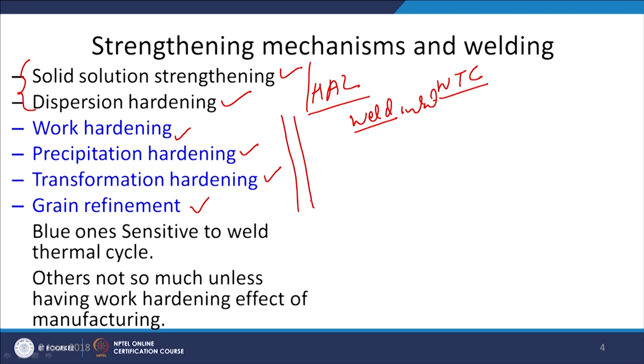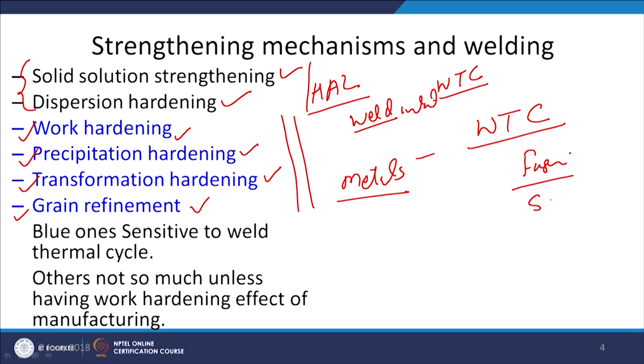On the other hand, all those which are highlighted in blue like work hardening, precipitation hardening, transformation hardening, and the grain refinement, properties of such kind of the metals which are strengthened by these four mechanisms, they are found to be extremely sensitive to the weld thermal cycle being imposed either during the fusion welding or during the solid state joining. The properties are going to be significantly affected, because in case of work hardening there will be loss of the dislocations, in case of the precipitation hardening there will be loss of the precipitates, in case of the transformation hardening there may be formation of the soft or the hard phases as per the type of metal system, and in case of the grain refinement, metals strengthened by the grain refinement, the weld thermal cycle will be leading to the grain coarsening, and which in turn will be deteriorating the hardness and the strength of the metal.